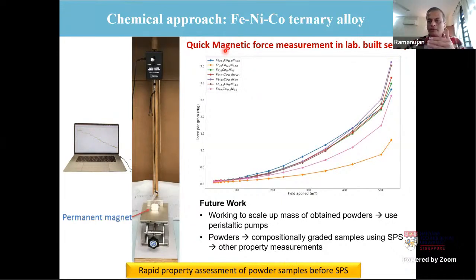So as these powders come out and are produced, we can use this magnetic force measurement, which is basically a permanent magnet connected to a force sensor, to find out which material is more likely to be magnetic. So this is a screening process in which we are able to filter out which compositions are more likely to be attractive. This is a technique which we have developed in our lab.